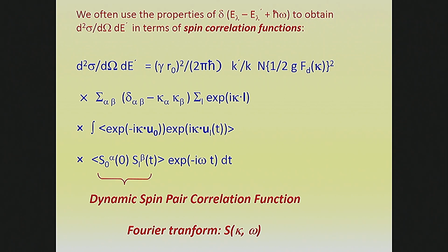This is a consequence of the dipole of the neutron interacting with the dipole of the electron moment. If you've got a dipole magnetic moment, it has a dipole magnetic field associated with it. It kind of looks like a butterfly, right? There are no magnetic field lines coming out along the moment. Is this familiar to anybody? Okay, good. So the magnetic field lines from a dipole come out in all directions except the direction of the dipole itself. If you've got two of these dipoles interacting with each other, their relative orientation is important. I'm just going to skip to the answer, and that gives you this term, which tells you that you are insensitive to moment components that point along the direction of the momentum transfer. It means that you will only see those components of magnetic moments which lie in a plane perpendicular to the momentum transfer.